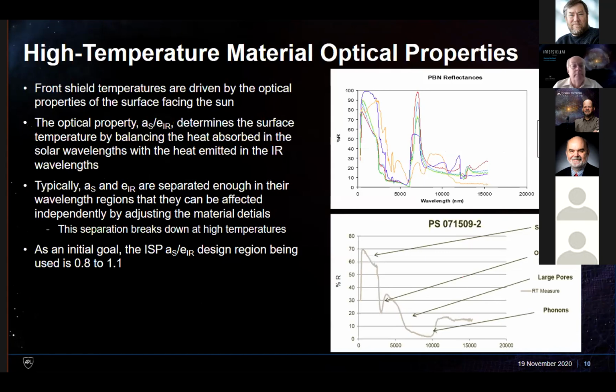Optical properties. Again, temperatures on the front surface are driven by optical properties, which is how the energy leaving the sun is absorbed or reflected by the surface. You can see there are some curves here. We're talking about a range of wavelengths. The visible is happening in the short range, and we have IR happening in the longer range. These are all curves that we took during the solar probe days for a variety of different things.